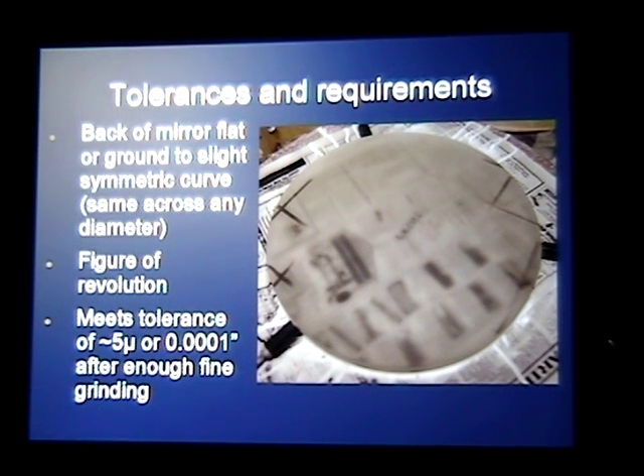And often, the actual reason for this right here is because it was annealed, and it changed shape as it was annealed after it was machined. So you have to go back and regrind and make things flat again because the strain released, the blank changed shape, and you have to watch out for that.